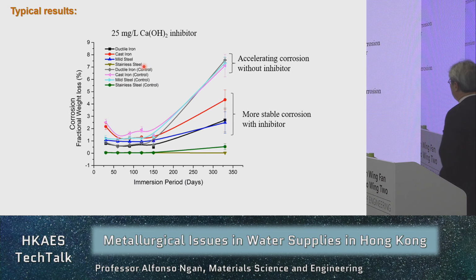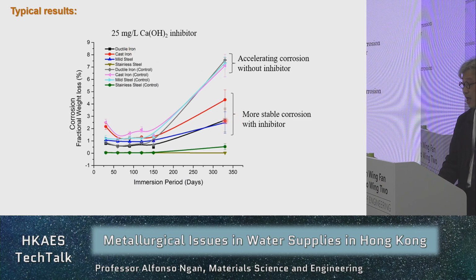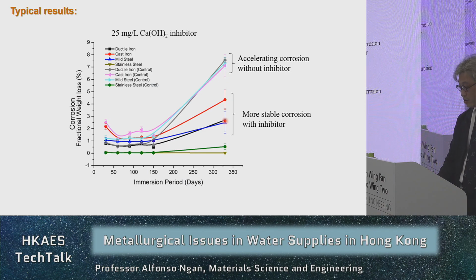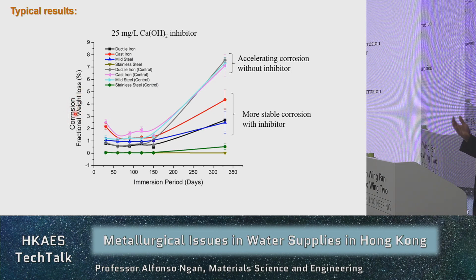And as you can see, for each metallic material, let's say if you take ductile iron, which is the black curve, if you have the calcium hydroxide added, the corrosion amount, so we measure the corrosion by the weight loss. So after the metal has been immersed, we took it out, polished off the rust, and measured the weight.